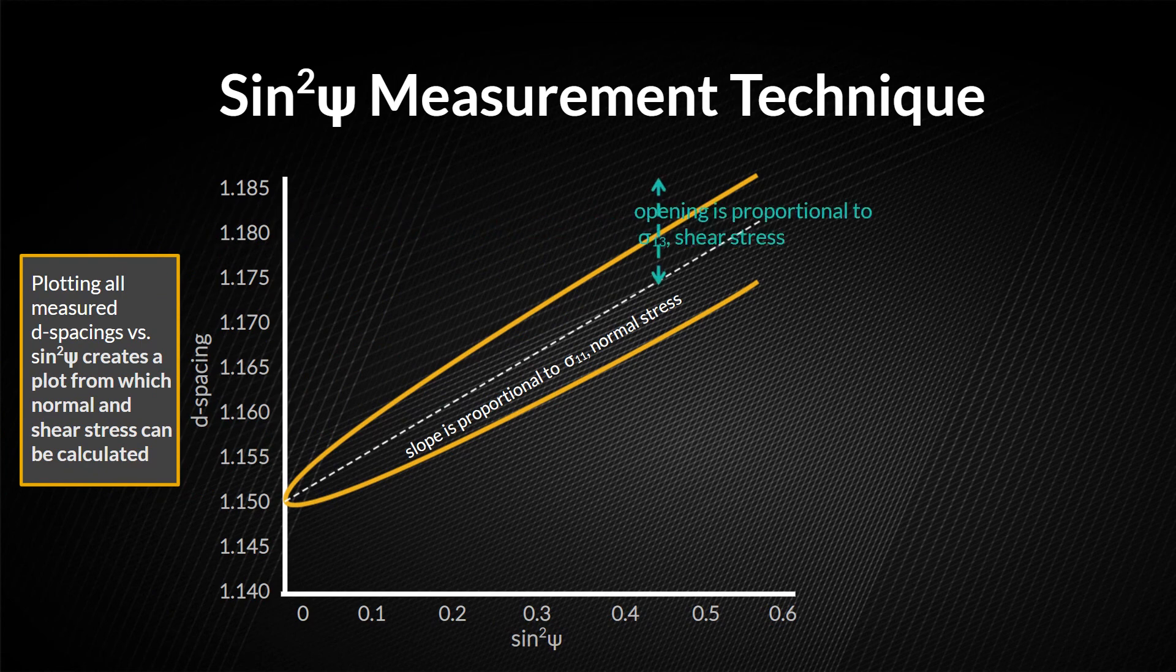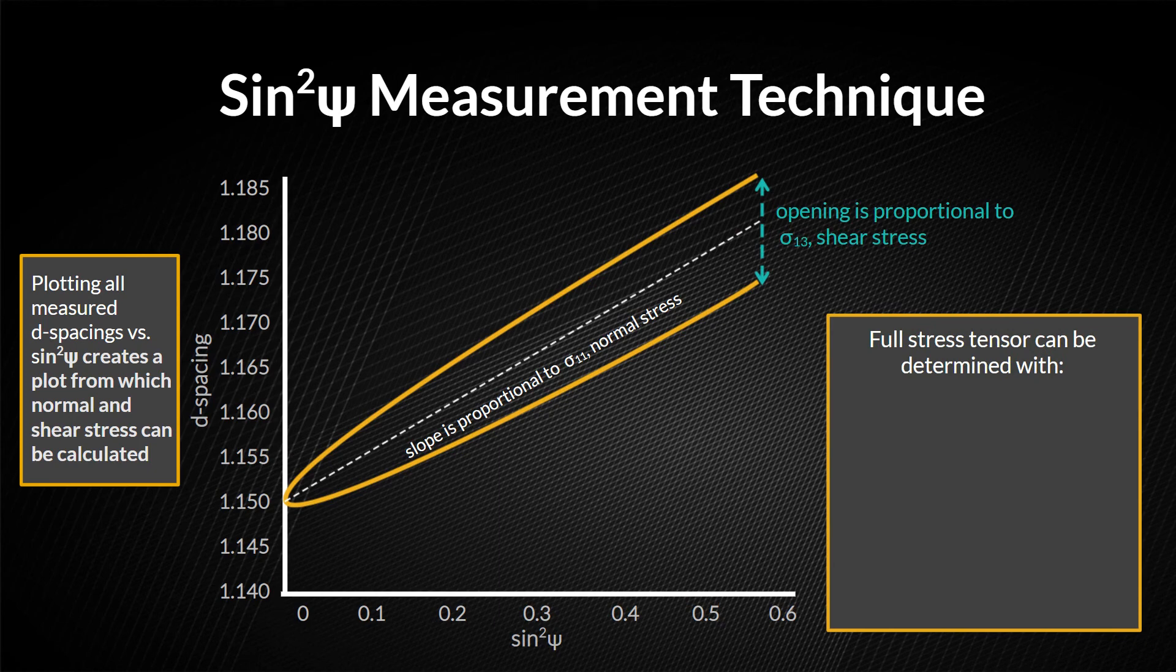From this plot, the normal stress sigma11 and shear stress sigma13 can be calculated. The full stress tensor can be determined by performing two additional measurements.